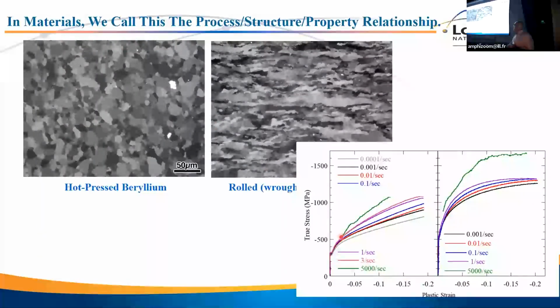Here is the stress strain curve of the wrought material at different strain rates, and the stress strain curve of the hot pressed material. The macroscopic properties of those two are very different. The flow strength is very different. The worked material is much stronger. That's the microstructure that links the processing to the properties.